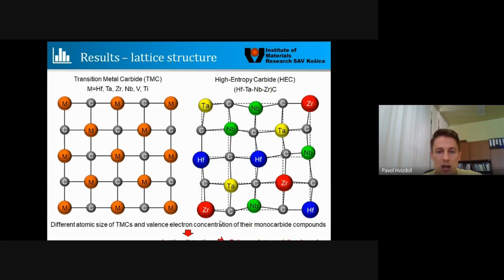So it means we got something which can be shown on this scheme. We started from transition metal carbides, which have a cubic, sodium chloride structure, where the metal elements can be hafnium, tantalum, zirconium, niobium, vanadium, titanium. Those are the group 4 and group 5 transition metals. But once we mix them and subject them to SPS, due to diffusion, metallic elements are replaced by each other randomly, as was confirmed previously by EDS and STEM analysis, forming a structure similar to the one shown on the right side, where we can see randomly distributed transition metal elements in this sodium chloride structure, which generates a lattice distortion.